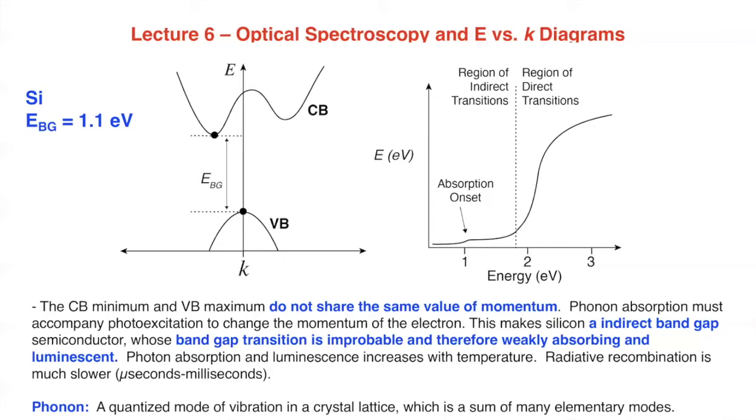And silicon still does photoluminescence. It's just weak, and it still does this unallowed optical transition. And those things are actually assisted by vibrations. So if the optical transition couples with the vibrational transition, where both things cause the excitation at the same time, then you'll start to see absorption and photoluminescence. And that makes those transitions temperature dependent. So with higher temperature, there's a greater concentration of phonons, of vibrational excited states, and a wider range of energies, and as a result, the probability of those improbable transitions, the unallowed ones, goes up.